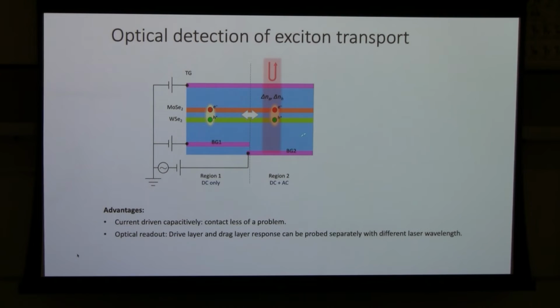So what will happen if you modulate this gate? Let's assume the electrons and holes are not forming excitons, so you have free moving charges. Then if you apply, say, a negative gate voltage, it will attract the holes, or it will push electrons away. On the other hand, if you have bound excitons and you apply a gate voltage, what you can think is happening is you will change the effective electric field over here. As a result, you modulate the energy of the exciton, so it will be able to drive an exciton current flow. So with this gate voltage, we will use optical readout to measure